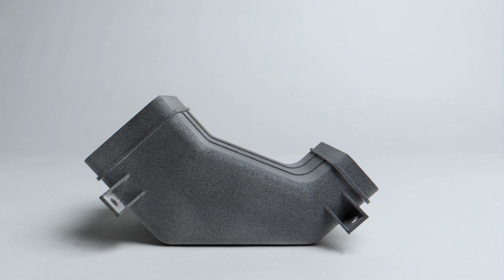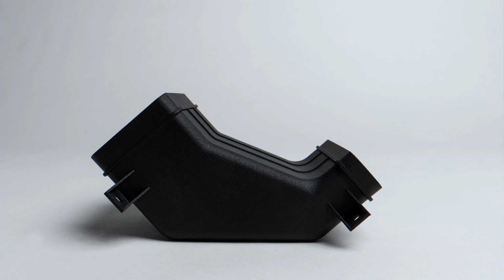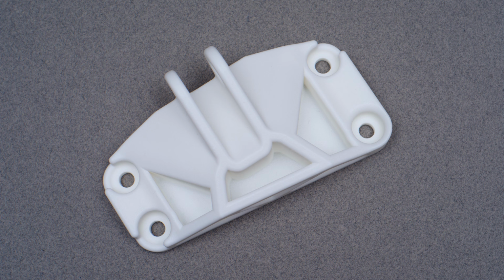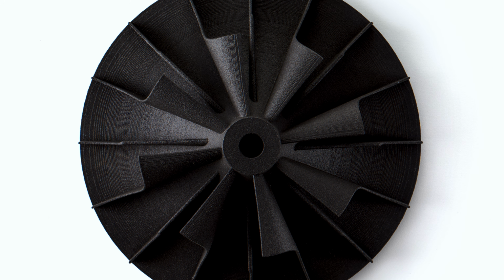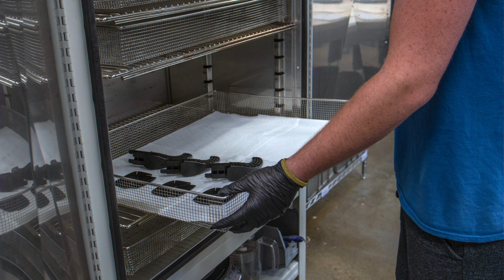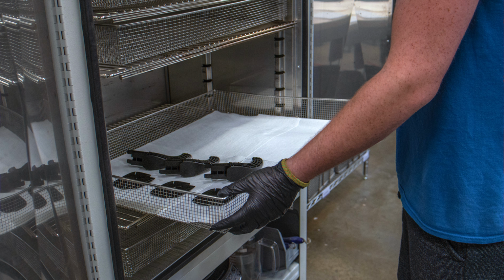Now, MJF versus SLS nuances. On MJF, black dye takes a gray core to a deep, uniform black. It's the fastest route to a premium aesthetic without changing mechanics. On SLS, you are going from white to black, which not only upgrades the look, but also masks the light yellowing that white nylon can show over time under ambient UV. In both cases, the mechanical properties are essentially unchanged. The dye step is low energy compared to the sintering process that built the part.